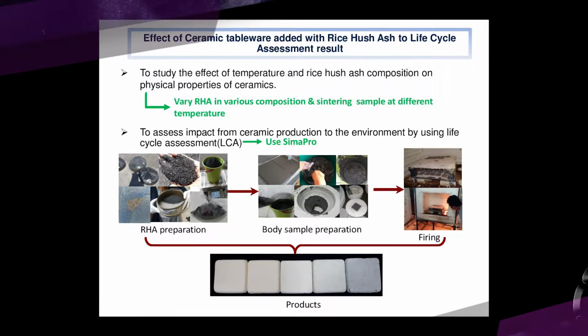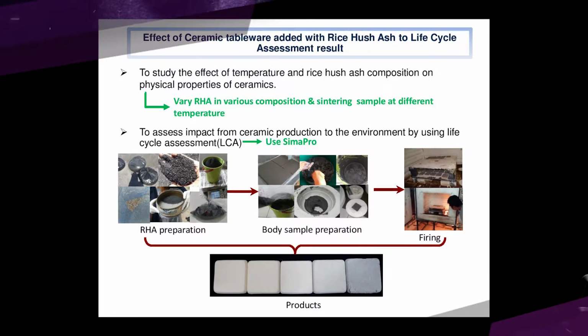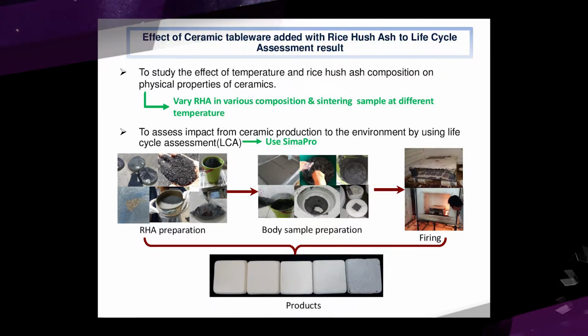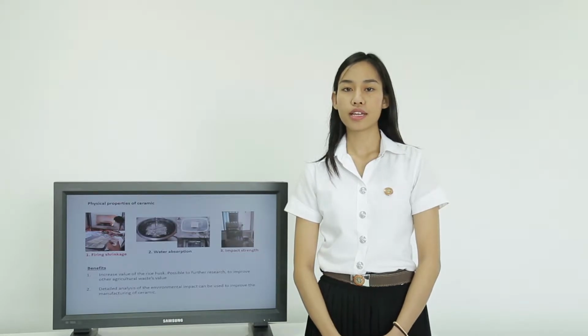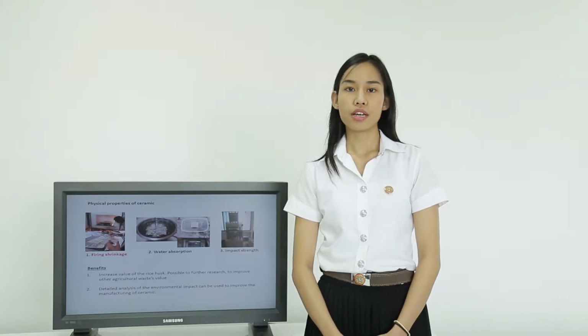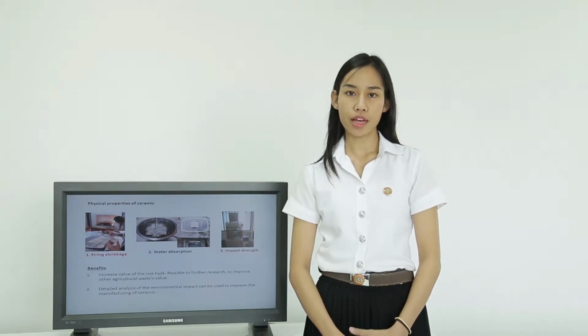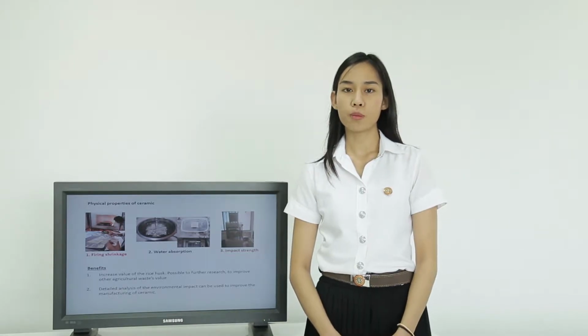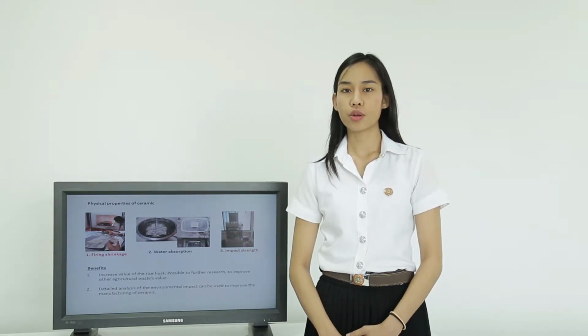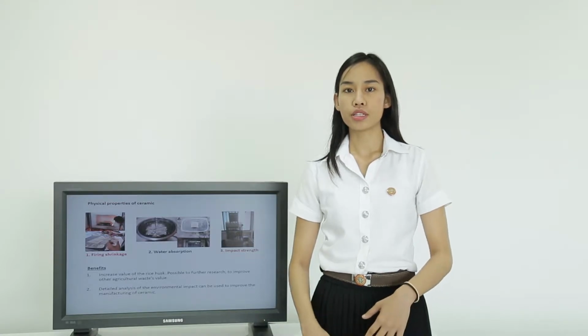Ceramic samples were then treated at different temperatures of 800, 1000, 1100, and 1200 degrees Celsius, and three properties, such as water absorption, firing shrinkage, and impact strength, should be tested, because we have different compositions and different temperatures, so the results should show different data. For analysis and evaluation of the environmental impact, I employ the SimaPro software to conduct the assessment.